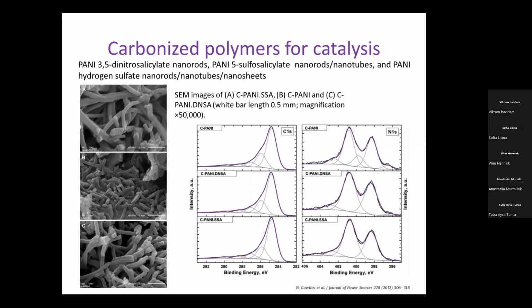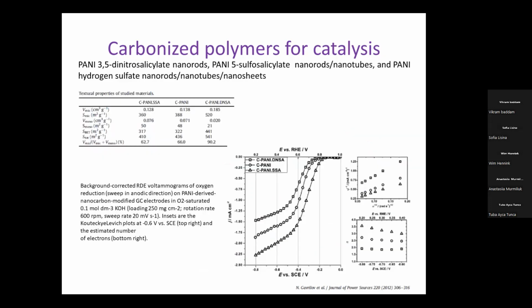We have heteroatoms, nitrogen incorporated in the structure, in the surface, as seen by the XPS. And we get different properties of these materials in terms of textural properties. And this is certainly reflected in electrocatalytic performance. So in this series of materials, we can actually optimize the synthesis so that we can either reduce oxygen to hydrogen peroxide or we can reduce it to water, which is really useful for different applications.